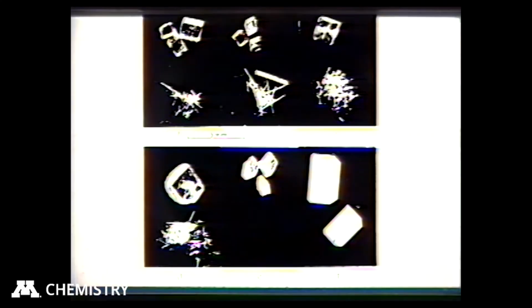Now the other nice benefit of using something like triphenylphosphine oxide is that it's a big molecule. And if you don't have very much material and you're trying to crystallize it, you can increase its molecular weight by incorporating triphenylphosphine oxide in. And you might even have several phenol or amine or amide groups, and you might be able to bring in 2, 3, or 4 triphenylphosphine oxides and have a lot more bulk to work with, and also have the chances of making better crystals from the material that you're working with. So this trick has really worked nicely in a lot of cases.